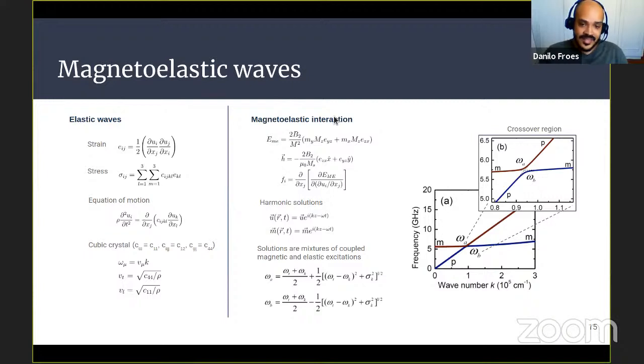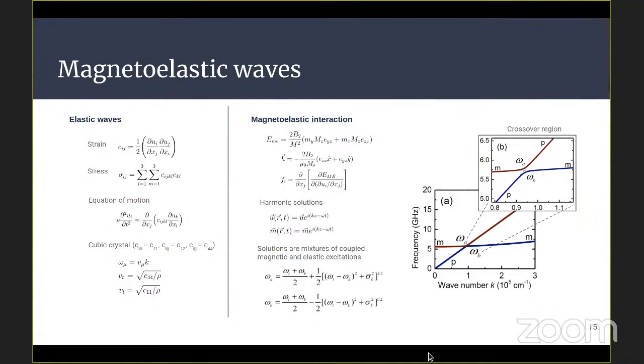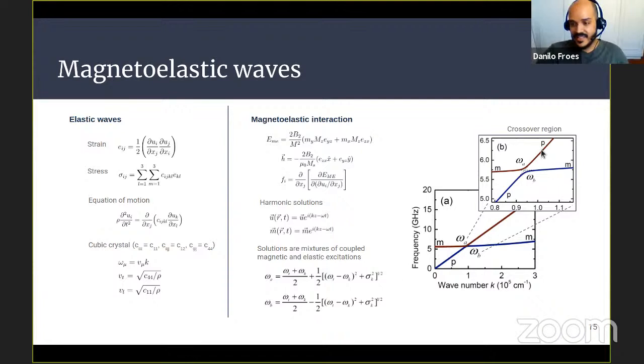When we're talking about a magnetoelastic interaction, we have an effective magnetoelastic energy. From this, we can calculate the effective magnetic field, a magnetic field that depends on strain. We can also calculate an effective force, which goes in the equation of motion for the elastic waves, and this depends on the magnetization. So we have a magnetoelastic feedback there. If you look for harmonic solutions for both displacement and magnetization, these are the equations we obtain. You can see the separation in two branches, magnon-like and phonon-like, with an anti-crossing between them. The anti-crossing distance here is proportional to the intensity of the coupling between them.